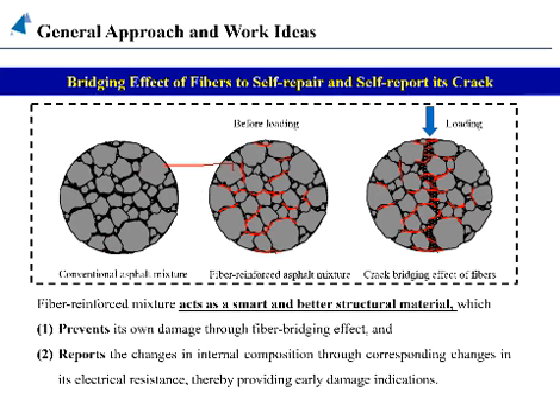This is the conventional mixer. These are the aggregates, these are the voids or spaces, and the asphalt binder is basically here. So what I did, I put in fibers. The red ones show basically the carbon fibers, which reinforced the mixer. When I applied loading and some cracks were generated in the mixer, these fibers basically reinforced this crack. Here I applied tensile loading. In another experiment, when I applied compressive loading like this, these cracks were recovered like this.